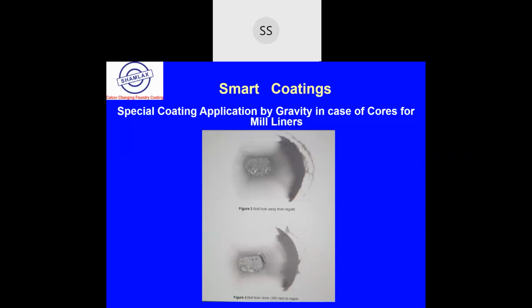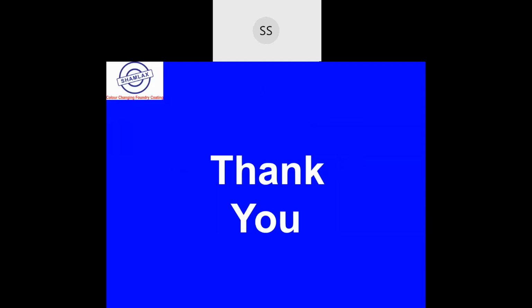So here the coating parameters, particularly the color changing feature of the coating, are very important. After drying, the cores are kept inside the oven at 90 degrees, because normally the foundries are producing a number of cores and storing them at a temperature of around 90 degrees so that they can be used whenever required. That's all in short from my side because the time limit was there, and I wanted you to get a feel of the color changing phenomena of these coatings.